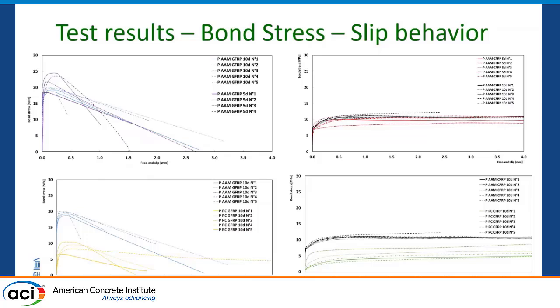In the upper left corner, you can see GFRP, the alkali-activated mortar for 5D and for 10D. So we see that the behavior is similar, that on average 5D experiences a little higher. And here we can see the comparison of alkali-activated mortar with GFRP for 10D and PC mortar with GFRP for 10D. We see clear increase in the bond stress, but overall behavior is the same.